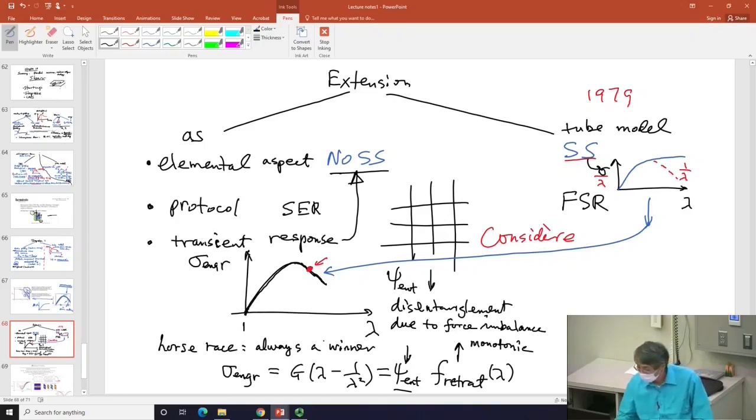In other words, when you apply the Considère criterion, you are at a continuum level. You are not worrying about a more elementary question, which is what happened to give you the force dropping? Instead, as soon as you see force dropping, you conclude using this effect, saying that's the cause. Cause of what? Cause of necking and inhomogeneous extension.